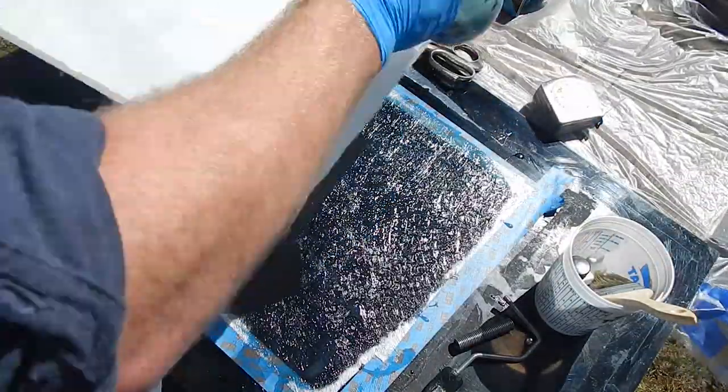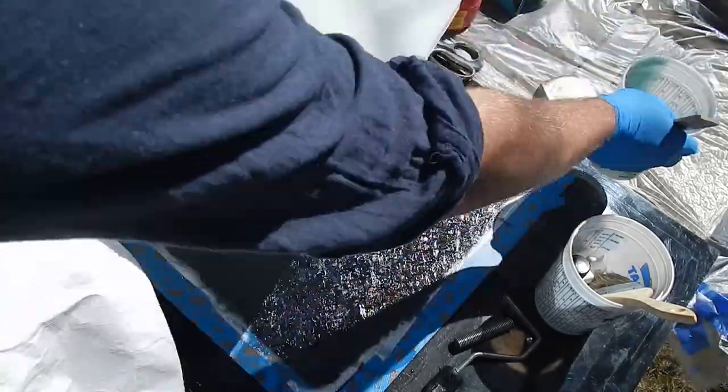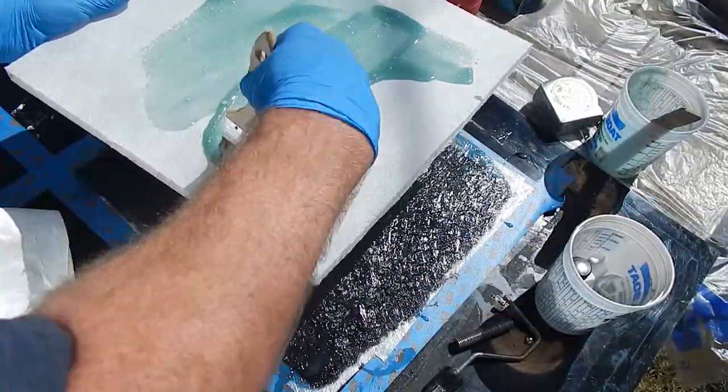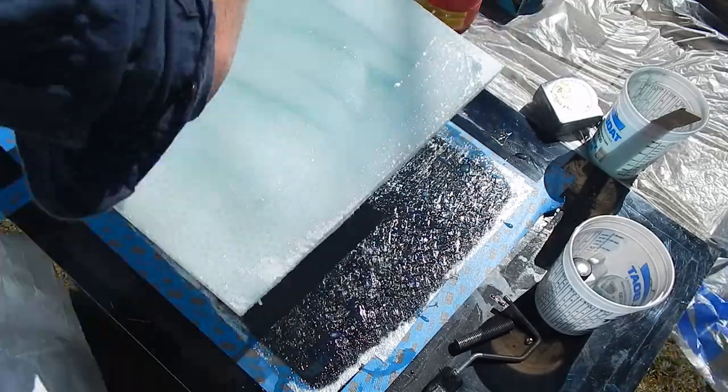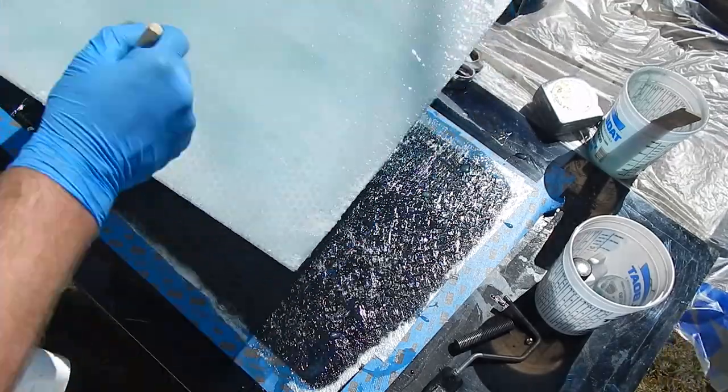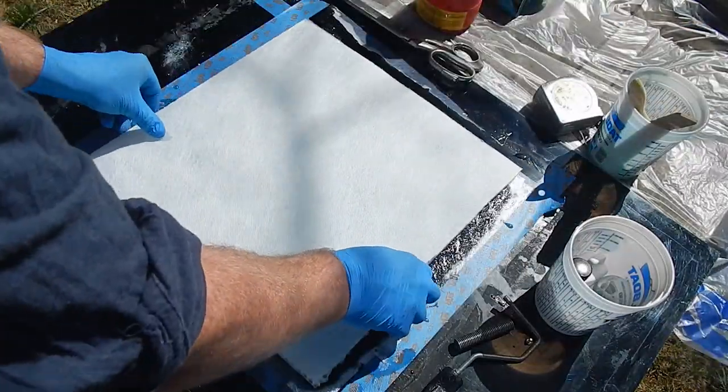And this thickens it up and makes it less likely to run out. This is pretty thin for core bedding. In most cases you'd want it thicker, but I'm doing it into wet layup instead of something that's pre-cured.